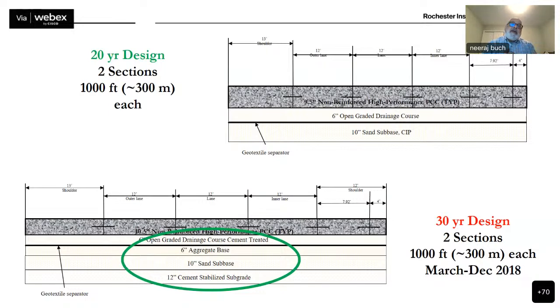So there was a significant foundation layer under the concrete pavement. The other significant difference between the 20-year design and the 30-year design, besides the 10-year design difference, was the diameter of the dowel bars. So for the 20-year design, the diameter of the dowel bar was 1.25 inches, whereas the diameter of the dowel bars for the thicker pavement, the 10.5-inch pavement, was 1.5 inches or 38 millimeters, as I had noted in my previous slide. So again, this gives you sort of a structural comparison between the 20-year design and the 30-year design.